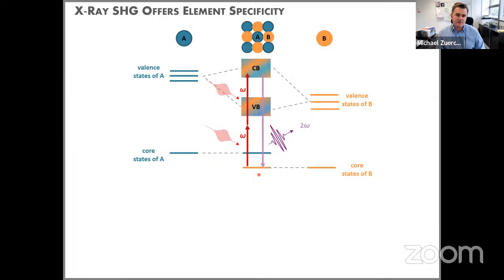So whether we can actually do second harmonic spectroscopy with core electrons. And that is what a simplistic version of an energy diagram can look like. Instead of linear X-ray absorption spectroscopy, where one would use one photon to transition resonantly between a core and the valence state, can we instead use, for example, photons of half the energy, trigger a resonant transition to a valence state, and observe the second harmonic of the signal, basically adopting second harmonic spectroscopy from the visible and mid-infrared to X-rays?